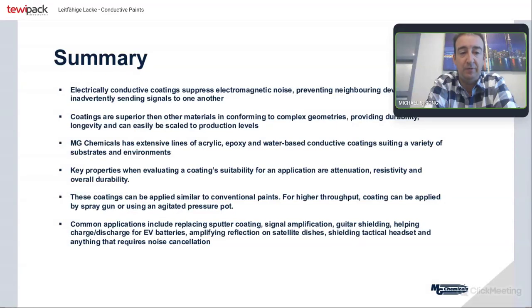Some of the key properties when evaluating a coating's suitability for an application are the attenuation, and we did see that graph that I presented for the acrylic series, resistivity, and the overall durability, which is a catchphrase for what is the polymer system, how does it work depending on the stress it's going to be subjected to in its immediate environment. These coatings can be applied similar to conventional paints. For higher throughputs, coating can be applied by spray gun or used in an agitated pressure pot, so it's very easy to scale. And once you have that system in place, you can do a lot of parts very quickly and very efficiently.